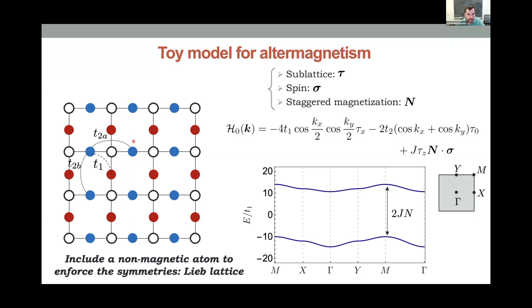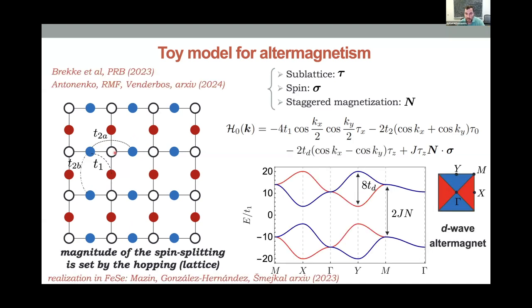But now, if you implement this crystalline effect, these symmetries imposed by the crystal, I have a new term in my Hamiltonian, and what you see is that you now open a splitting between spin up and spin down bands, not a gap. And this happens everywhere in the Brillouin zone except along the diagonals, and you get the d-wave altermagnet.